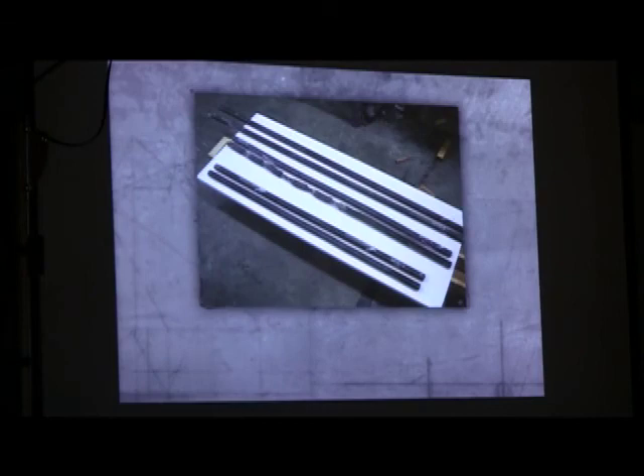These are examples of the extruded rod, and in the middle you see an example of what happens when you add heat to something that's already a little too close to the melting point. Towards the end of one of those middle rods, you see how it looks like something's a little strange with it? Well, that's a whole bunch of silver that melted when it went through the extrusion press, and the can couldn't contain it because it was liquid at this point, and it broke. But we did a lot of different experiments and came up with some really interesting combinations.